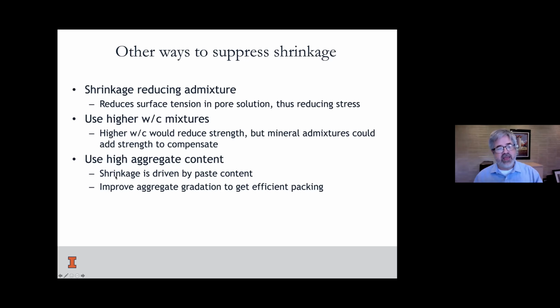And there's another thing, that we want concrete that flows. We want SCC. And these materials tend to have high paste content. So we're begging for a problem when we create some of these new materials that are really high paste, and it's going to have high shrinkage and so forth. So recognize when you make these trade-offs what's happening. Don't stumble into these low water cement ratios and high paste content issues just because you're not paying attention.